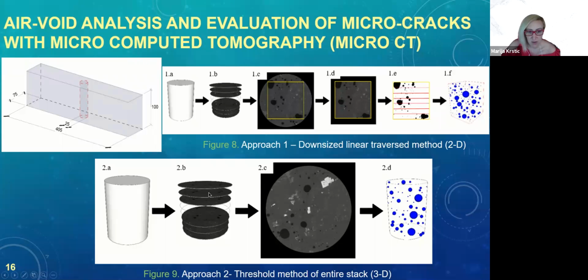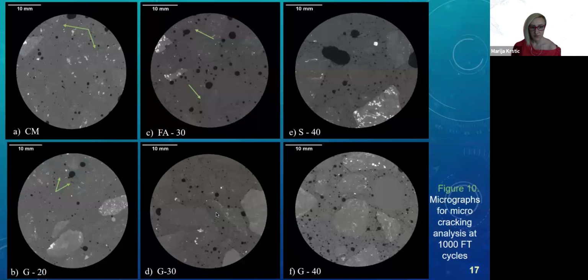A second approach was that we took the entire image stack of a core sample, and we basically applied image analysis for the entire stack. These micrographs were from the beams that were exposed to freeze-thaw cycles, and we tried to see if there were any microcracks. However, we were not really able to spot any, maybe because they self-healed after some time, or maybe simply there were not any cracks. All we were able to see was some microporosity, where you see those arrows, and this microporosity was just around the aggregates.